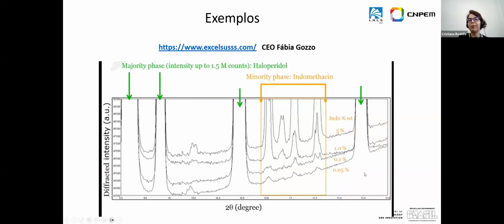This was performed at the ESRF in a powder diffraction beamline there that Graciele has shown to us before. And she could identify just 0.05% of this phase in the mixture in the pharmaceutical sample, because there she could work in high resolution. She had a better signal to noise ratio, and the signal improved. So it's just to show the power of using a synchrotron facility to study this pharmaceutical sample, and the previous experiment with a ceramic too.